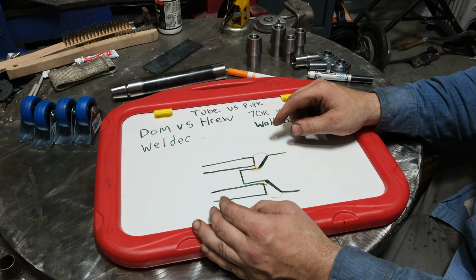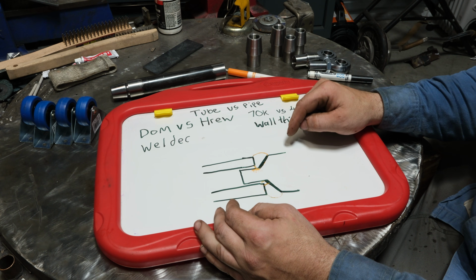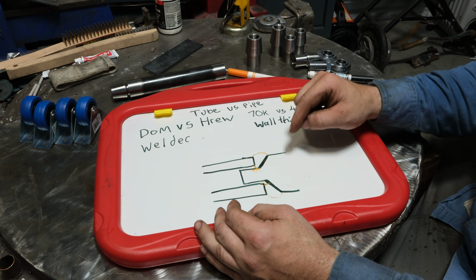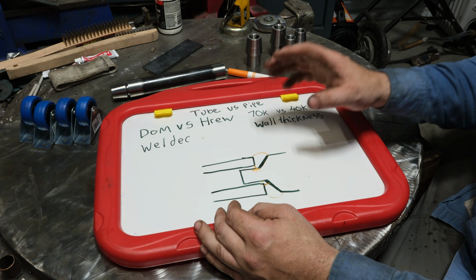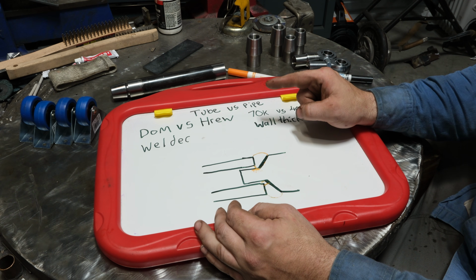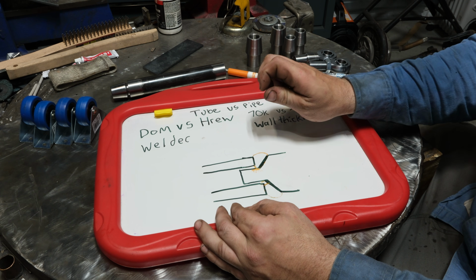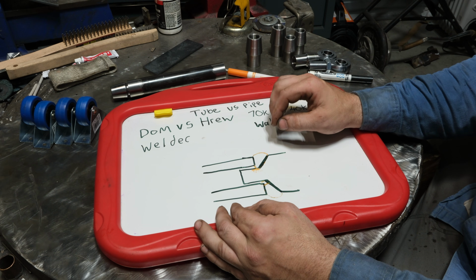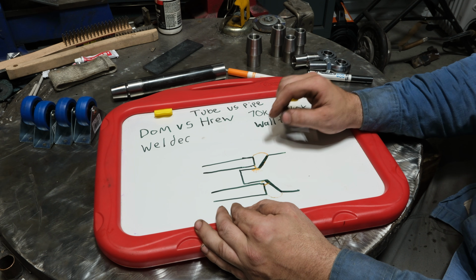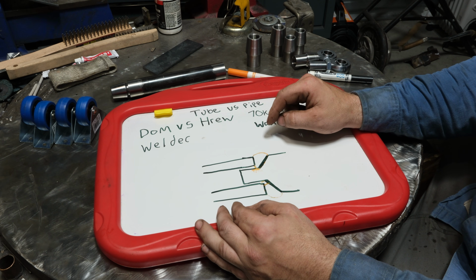Like I've showed in numerous videos, when you do that, you get a lack of fusion going over the tack. So before the tack and after the tack, you have a lack of fusion. Now, if you wanted to TIG weld it and you TIG weld tacked it, you'd probably be all right because of how thin that is and because of the TIG process. But with MIG, the last thing you want to do is a giant tack on that.